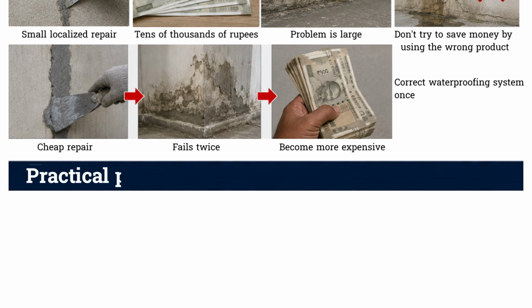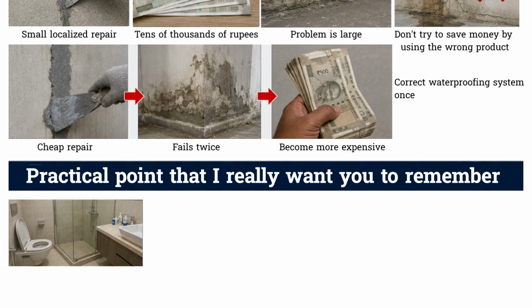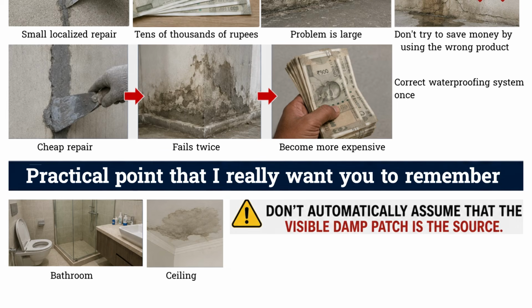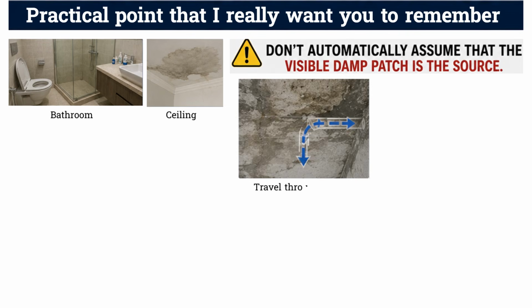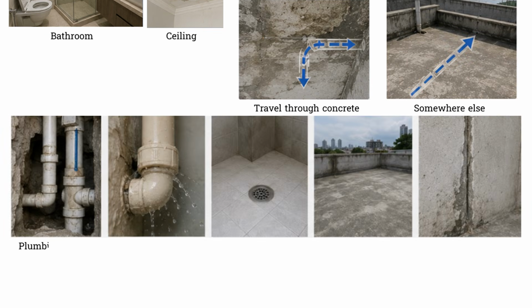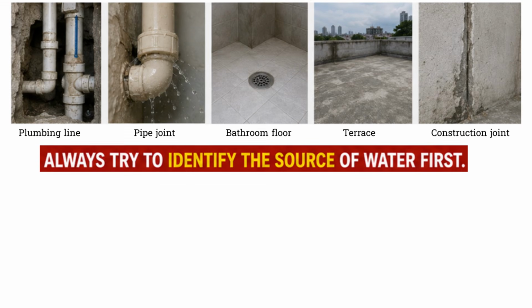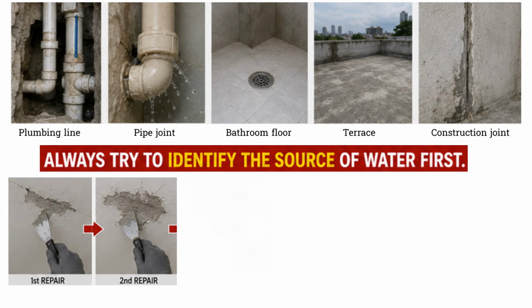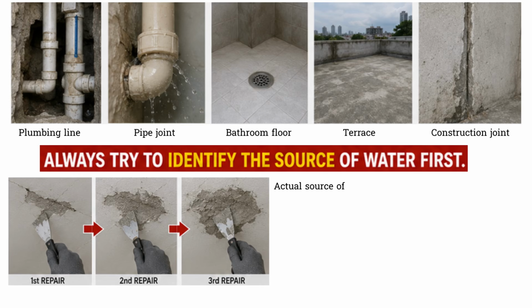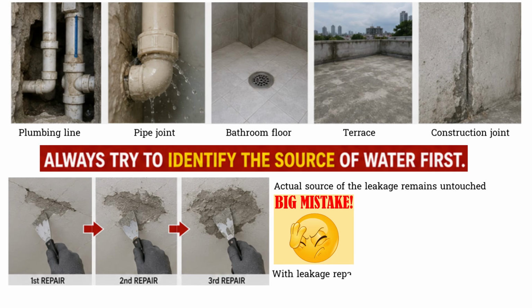And there is one more practical point that I really want you to remember. If the leakage is coming from your bathroom or ceiling, don't automatically assume that the visible damp patch is the source. Water can travel through concrete. The actual source could be somewhere else. It could be a plumbing line, a pipe joint, a bathroom floor, a terrace, or a construction joint. So always try to identify the source of water first. Otherwise, you may keep repairing the same visible crack again and again, while the actual source of the leakage remains untouched. And that is one of the biggest mistakes people make with leakage repairs.